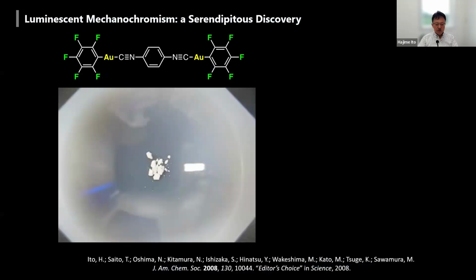During our study for developing new reactions for organic synthesis, we found that this gold complex can show some very interesting optical properties. We tried to make some new catalyst using these compounds, but unfortunately this compound is very stable, and we cannot find any catalytic activity, any reactions by using this compound.